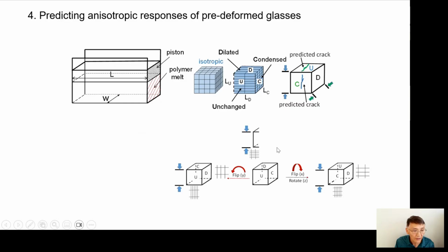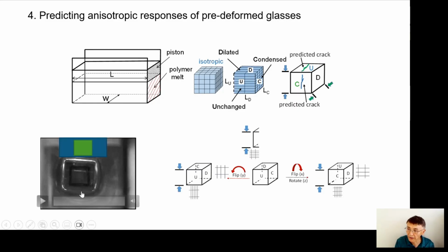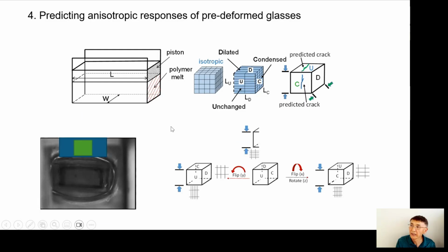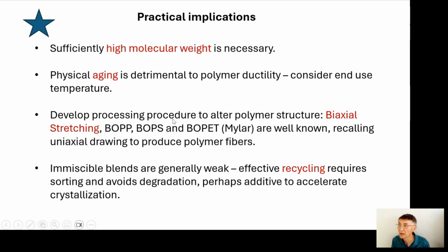I'm going to probably skip this. Basically, you can introduce anisotropy through squeezing in the melt state and explore this different effect of anisotropic networks. So, for example, when you have anisotropy, when you press a piece of material, the material no longer spreads isotropically, so it becomes elongated. In any case, this is my slides about implications.